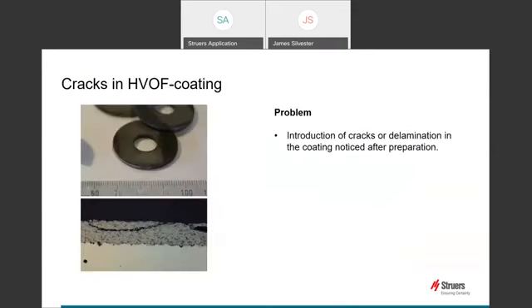If we look at a smaller sample, such as this washer with HVOF coating, this needed to be sectioned by cutting and then mounted and prepared for further metallurgical investigation. The challenge was to perform the cutting without introducing cracks or delaminating the brittle coating. The cracks can be seen on the screen. The customer had experienced cracking of the coating, and our challenge was to assist the customer to work out if the cracks were pre-existing or formed during the preparation process. The prime suspect for us was the manual cutting process causing excessive stress on this coating.